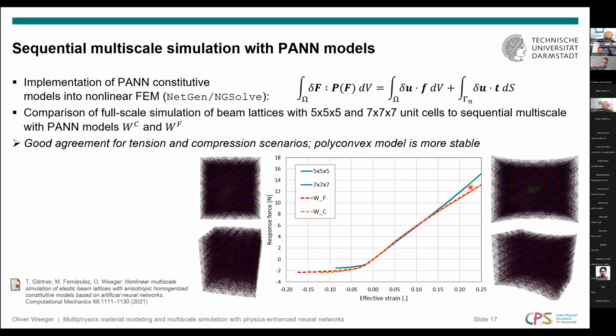For larger strains, it diverges here a little bit, which can have multiple reasons. It can be because the constitutive model is not accurate, but can also be because of boundary effects that happen in the simulation. But we also see here that the simulation in compression with the WC model, which is not polyconvex, not elliptic, terminates at some point, whereas for the WF model, which is polyconvex, you can simulate much more compression.